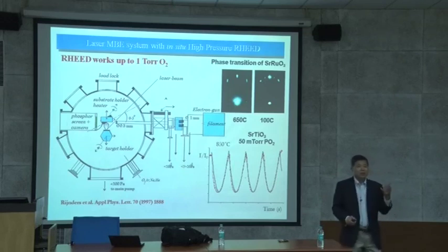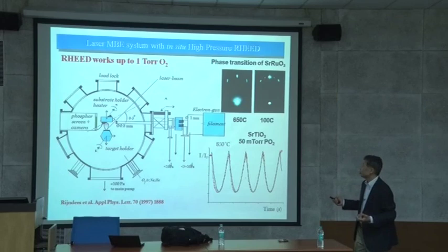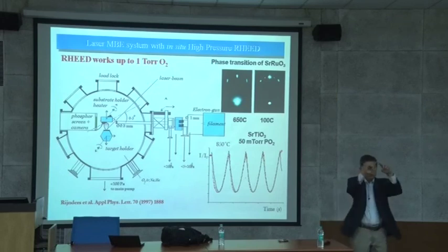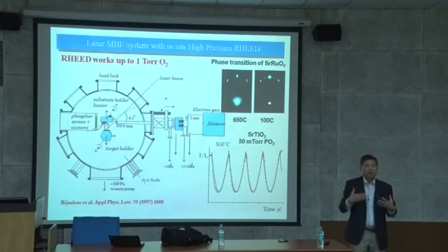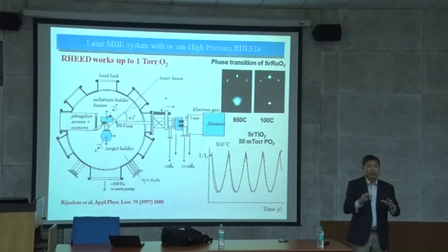That's why the quality of PLD thin films varies a lot, depending on how much you know and how much you control this. Sometimes we actually image the beam profile with an instrument, and you can image the whole thing. Then you know exactly what the energy profile is. It gives a three-dimensional plot, and then you can cut it to the good regions.